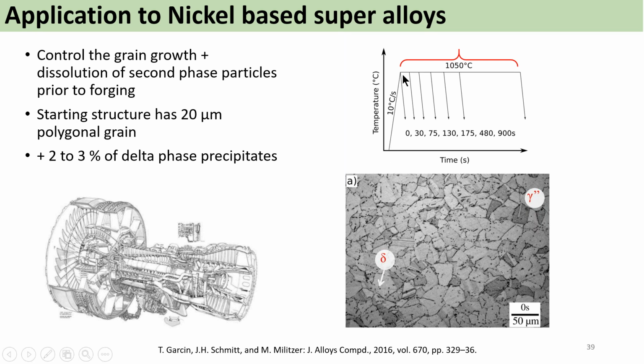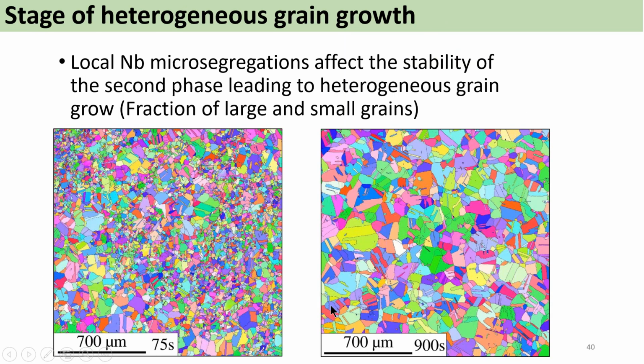What we have done is an isothermal holding at 1050 degrees, a typical temperature for homogenizing these alloys, and quenched the sample at different times. So I'm going to show you here the time of 75 seconds, which is early on in the beginning of holding. We see here that there are patches of grains which have grown substantially, while patches of grains have remained very small. And this is a typical sign that in those regions of small grains, the dissolution of precipitates has not yet occurred, pinning the grain boundaries and avoiding the growth of those grains. So this typical microstructure should not be kept at low temperature, as it would lead to quite heterogeneous microstructure during forging.